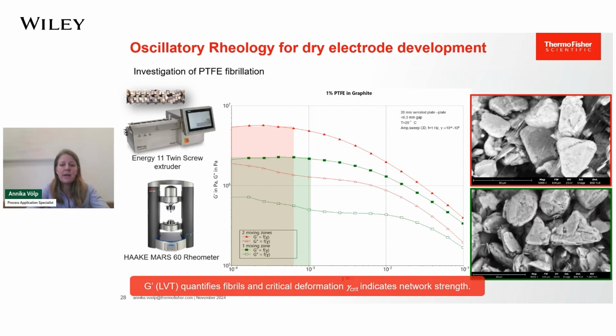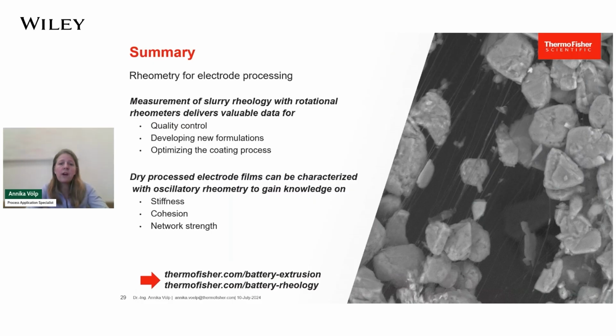So these results displayed show how oscillatory rheometry can be used to characterize the fibrillation and network strength in a dry PTFE electrode film. So summarizing this presentation on rheometry for battery electrode processing, I'd like to point out that measuring the slurry rheology with rotational rheometers does not only serve as a quality control tool, but also for developing new formulations, especially for tailoring the binder system. And it predicts the performance of the slurries in the coating process. A rotational rheometer can also be used to characterize viscoelasticity of dry processed electrode films in oscillatory deformation.